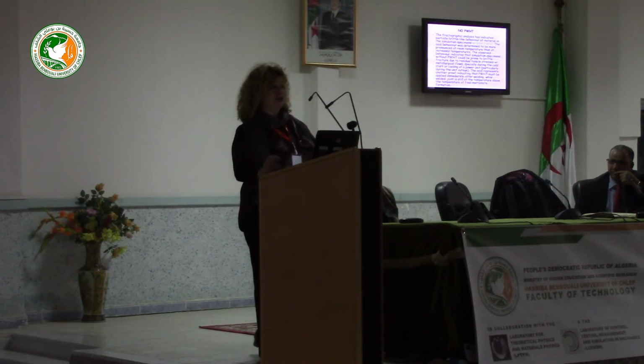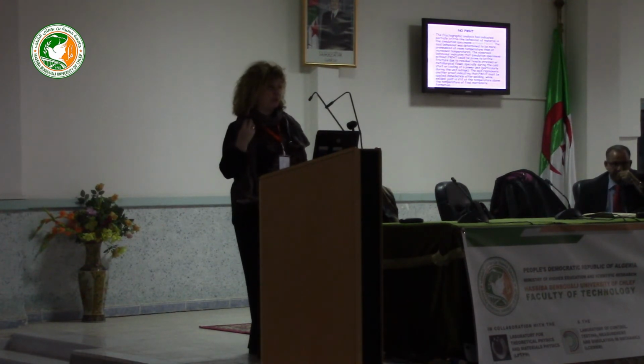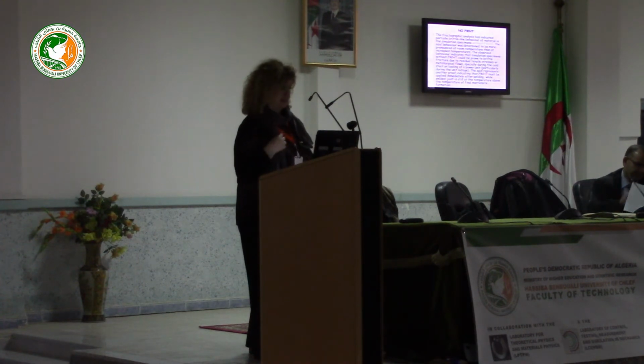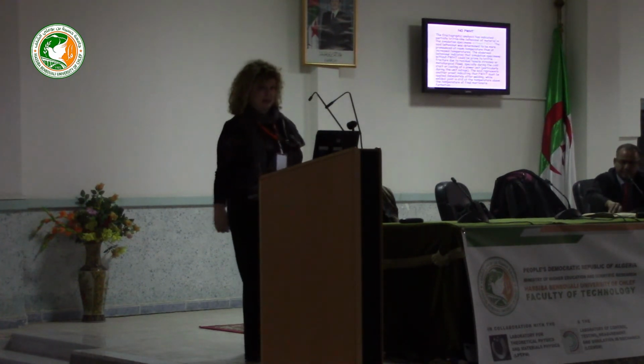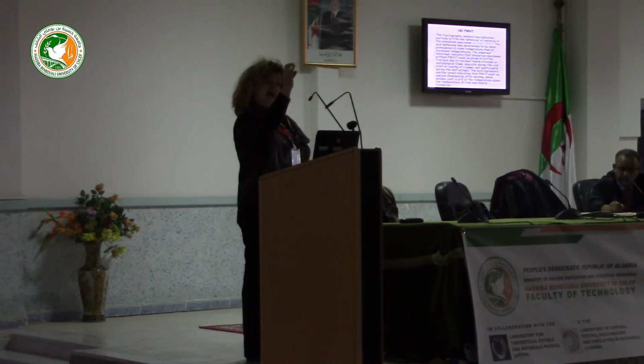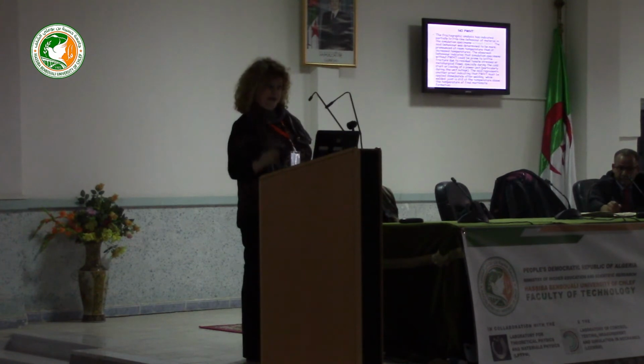Why? Because if we do not perform the post-weld heat treatment, we will have a very high level of residual stresses. And residual stresses are extremely dangerous when you have carbides precipitating in the grain boundaries. So they will fracture in a brittle manner.